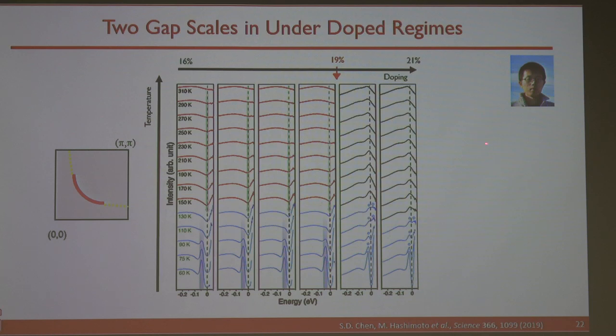One thing you can see, if I show you data at a high temperature, as a function of doping, you'll see this side and this side are very different. Okay? But if you only take the low temperature data, you find the difference is much more subtle. Okay? In this sense, if you quantitatively analyze it, they're still different, but it's much more subtle. Okay? So the thermal effect is clear.